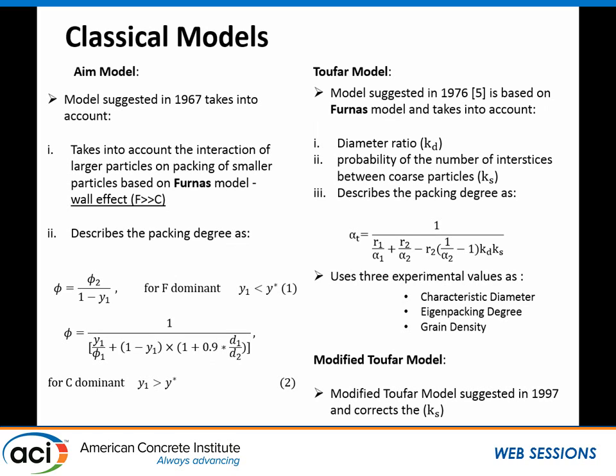If you want to talk about models, I found these two models to be relatively practical to use. They are both based on the Furnas model, but the difference is that the Aim model takes into account the interaction of large particles on the packing of the smaller particles, and they both have a dominant aggregate. So after a certain amount of fine fraction, the equation changes from a coarse dominant to a fine dominant mixture. It also describes that it's looking for the packing, not the grading here.